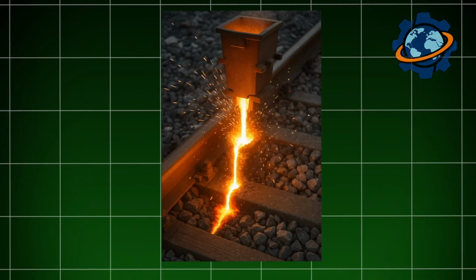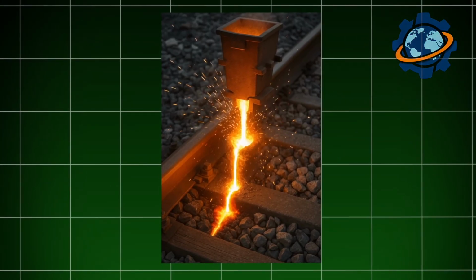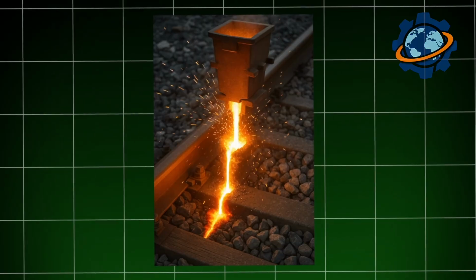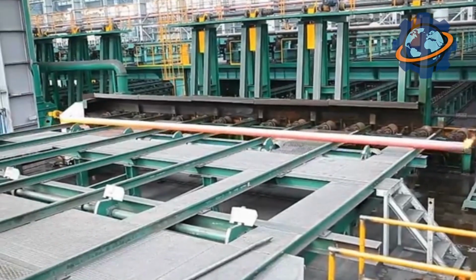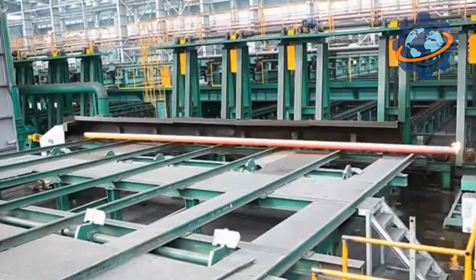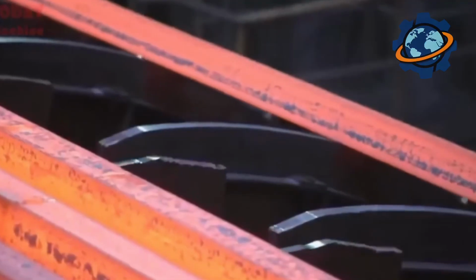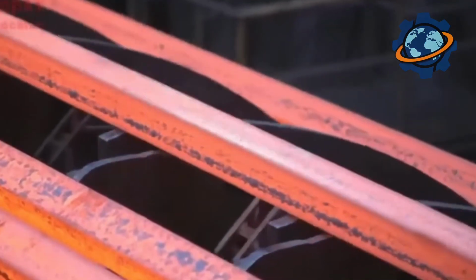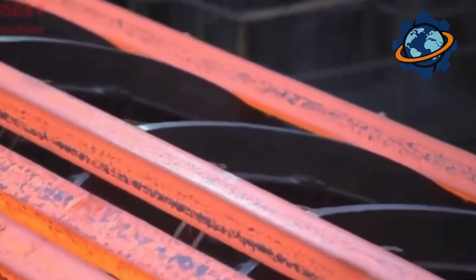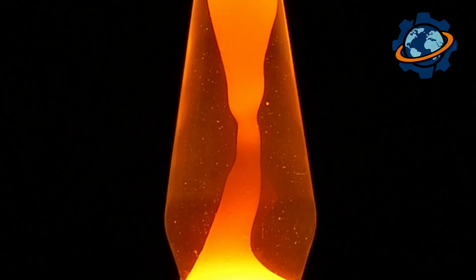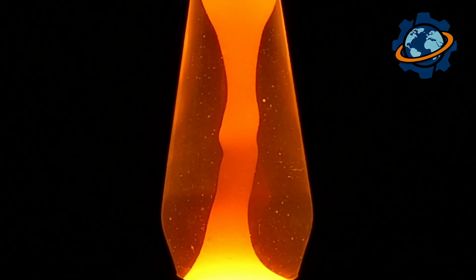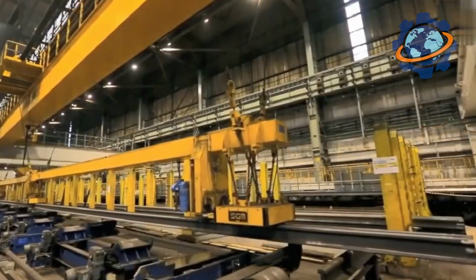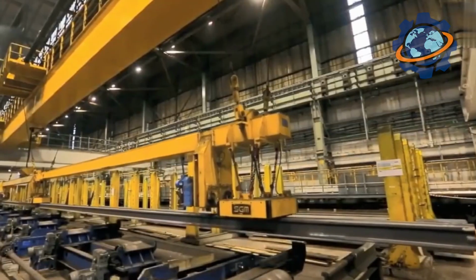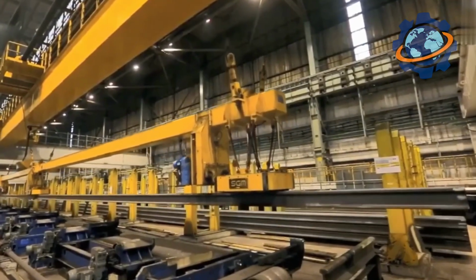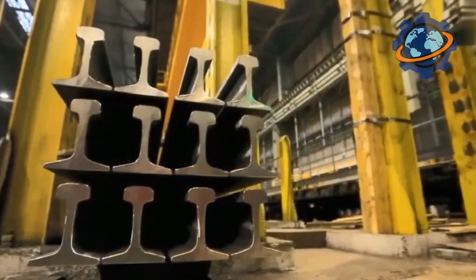In a special mold between two rails, a gap of a few millimeters is left. A molten steel mixture, created by the reaction of powdered aluminum with iron oxide, is poured in. The temperature hits a scorching 4,500 degrees Fahrenheit, 2,500 Celsius. This molten metal flows into both parts of the rail and fills the joint area. When it solidifies, it creates a monolithic bond, stronger than the rail itself.